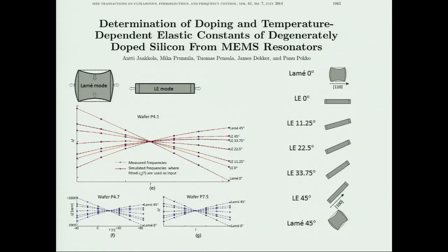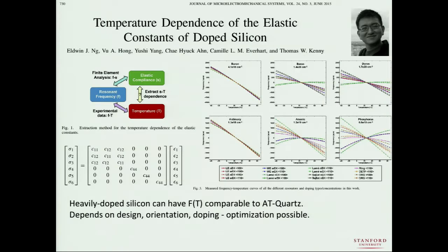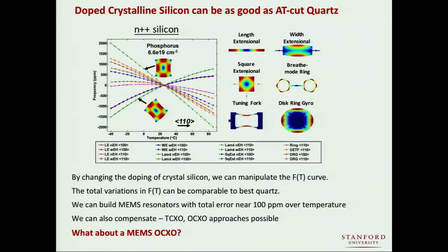But since then, we've actually, in the last decade, worked really hard to understand how to put this to use. Groups at VTT and at Stanford have done a lot of work measuring the temperature dependence of the elastic constants for different amounts of doping. We found resonator designs and combinations with orientation and doping that have much, much lower temperature dependence. And frankly, bring us to the place where the temperature dependence of the MEMS is comparable with the best quartz.